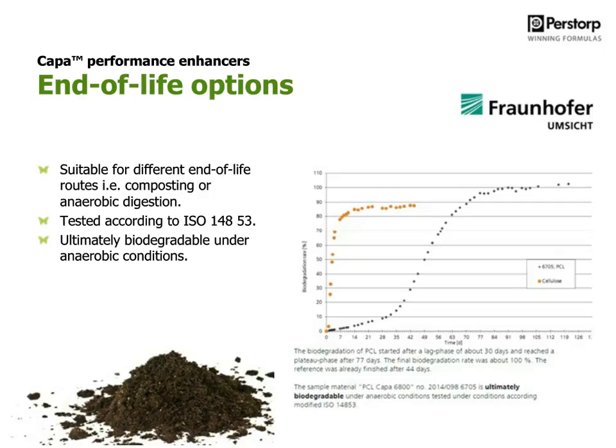And so with this test performed, we can show that within 77 days, the biodegradation is reaching its plateau, and more or less the entire sample has biodegraded under these pretty tough conditions as well, which is very good because that means that you really can select or use this polymer together with other biopolymers, and they can end up either in a composting facility or in biogas production and still biodegrade.